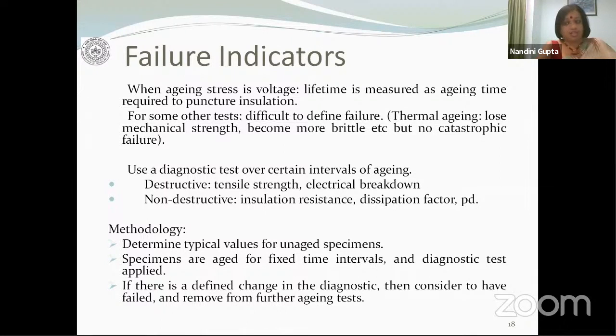But when we are looking at non-destructive situations, where some specific material property has degraded to the extent that the material becomes unfit for use, in that case, we would have to perform non-destructive tests to estimate the values of the parameter. Examples could be insulation resistance, dissipation factor, partial discharge. If the PD is of very high level, you may realize that it is going to lead to breakdown very quickly, and you might want to take appropriate action before unscheduled breakdown happens.